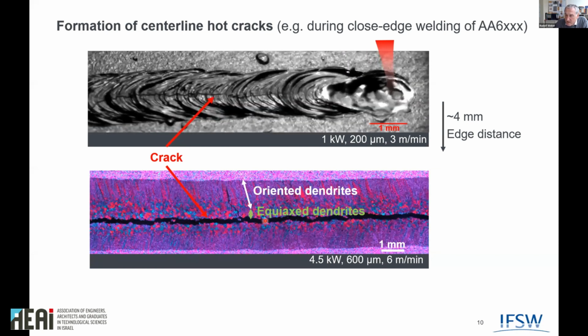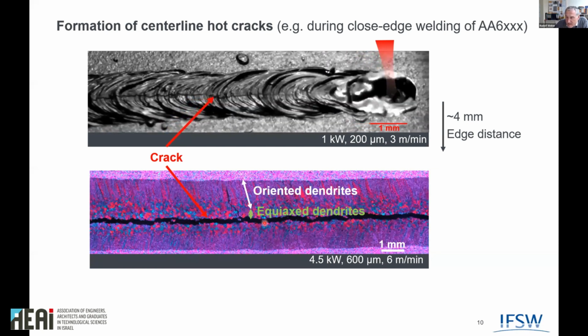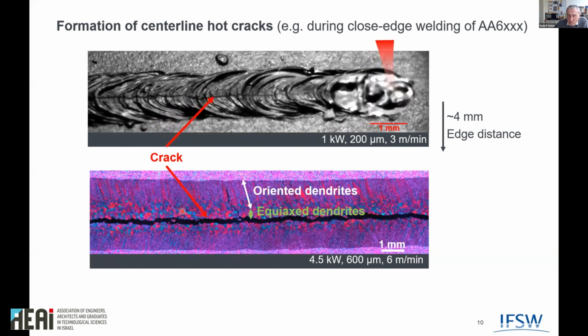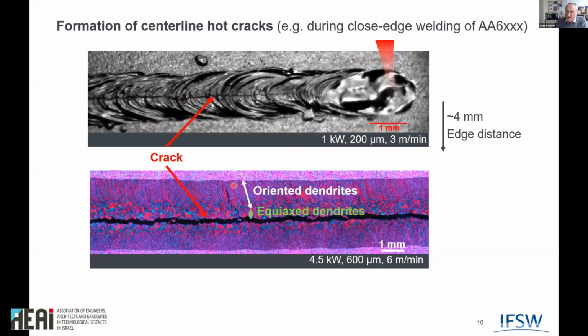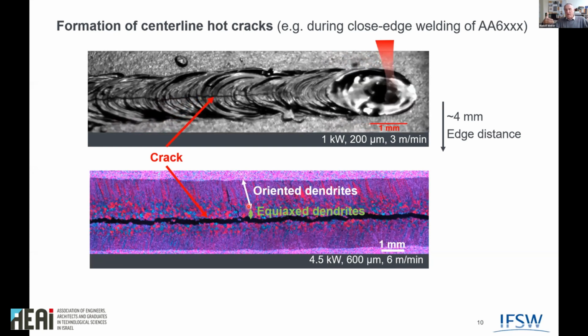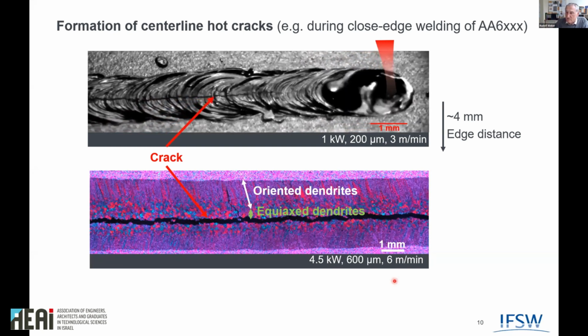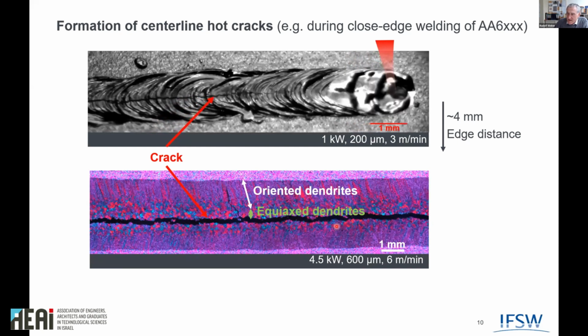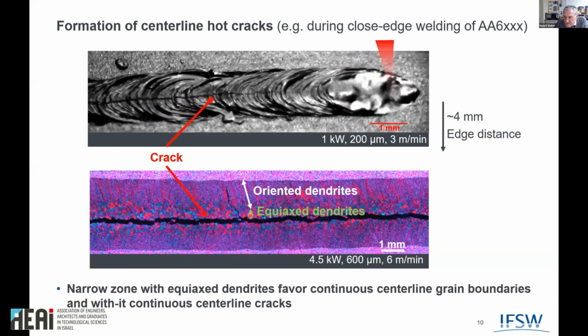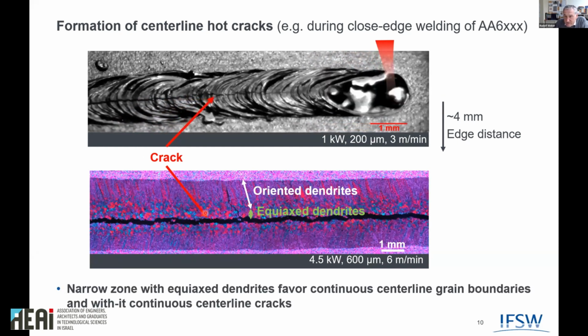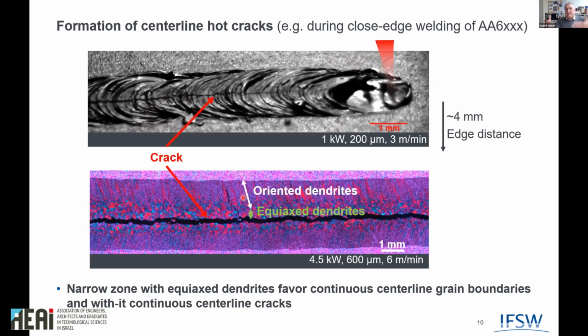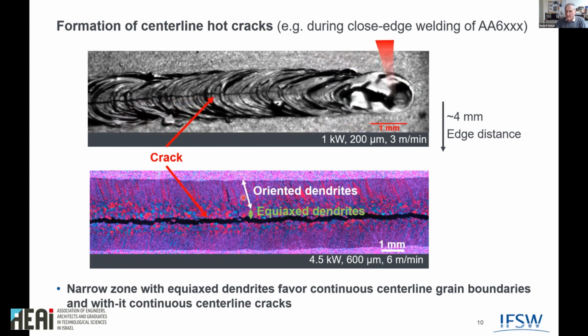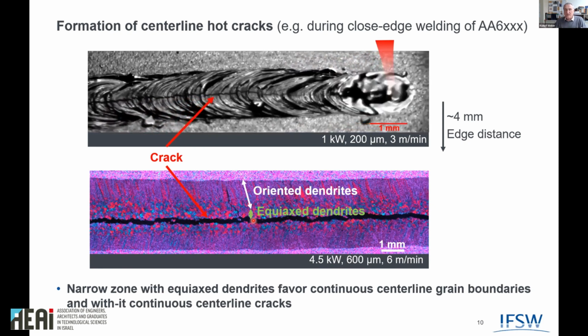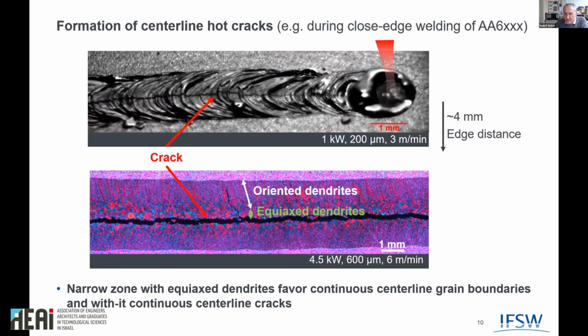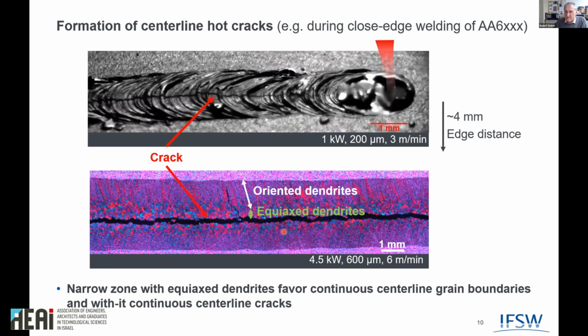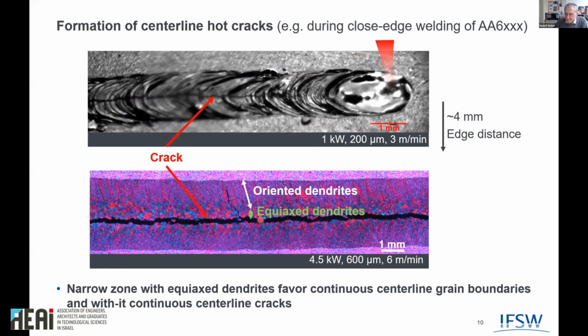We have a narrow band with so-called equiaxed dendrites, so kind of balls, and we have a kind of fingers here pointing to the center, which are called oriented dendrites. And the problem is, if this zone is very small or even does not exist, then we have these two fingers being very close to each other, which then very much favors the arising of such hot cracks because the mechanical strength is quite low.